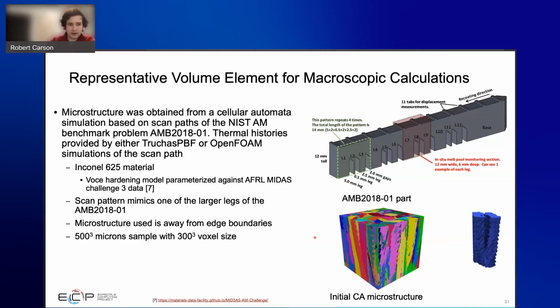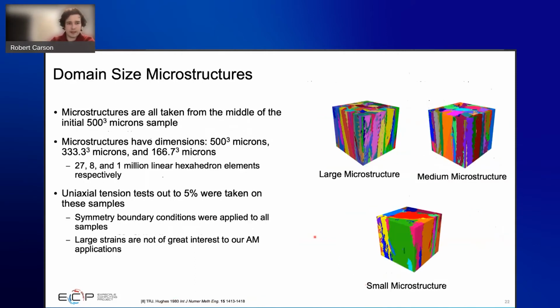Then we looked at what happens when we decrease the domain size and decrease the number of grains within each of the domains. We decreased it by thirds each time, so we went from 500 microns to 330 to 166 micron cubes. I'll mention that even though we were reducing the domain size, we still had fairly well-refined meshes. Even the small microstructure down here still had 1 million elements in it.